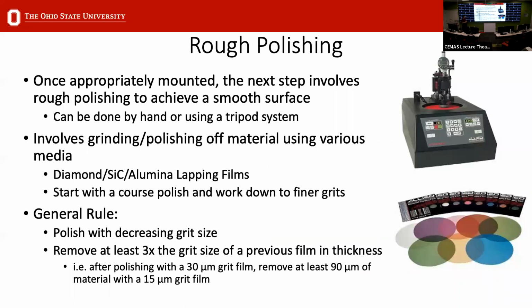So the first step, when you get your sample mounted properly, is rough polishing. This typically involves removing coarse layers of material to make your sample flat and to start to achieve smoothness. Historically, this is done by hand. Some people still use that technique, physically polishing by hand on various polishing media, but there are tripod systems now, configured for various size samples, and you can polish down your samples with that.